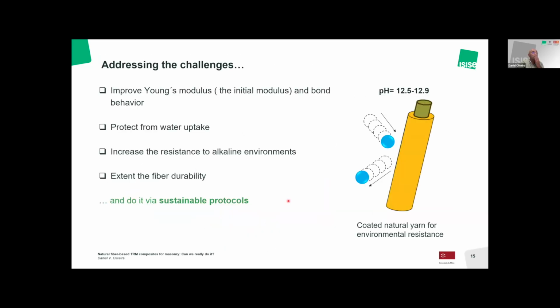So what to do? Well, if you can improve the initial elastic modulus that we saw in the graph, so you can have, let's say, a quite acceptable and straight segment, if you can protect the fibers from the water uptake, if you can increase the resistance of the fibers to alkaline environments, and if you can comply with these three requirements, you are also extending the durability of the fibers inside the mortar matrix. So if you can do this in a sustainable way, then you have a fantastic solution. So this is the main challenge we had.